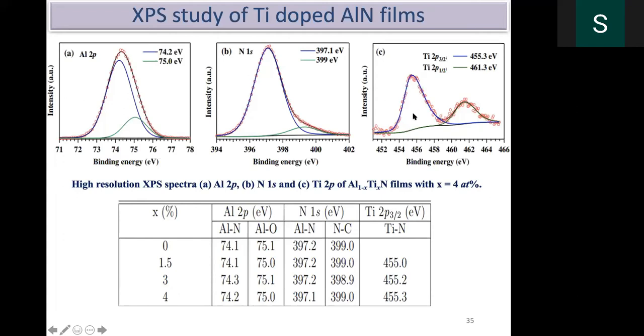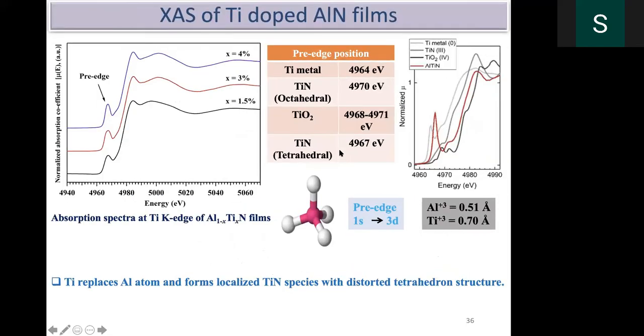That we can understand from X-ray absorption spectroscopy, how much this titanium goes and sits nearby the aluminum atom or replaces it. This is a very interesting technique. The X-rays go close to the atom, and from the reflection, you can find out whether the titanium replaces aluminum or sits on the aluminum sites. All those details we can find out.